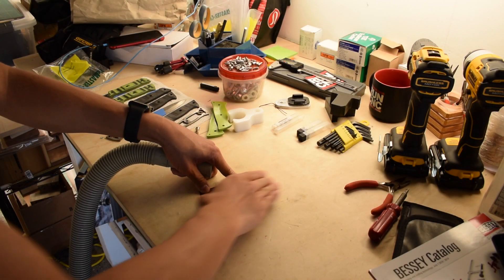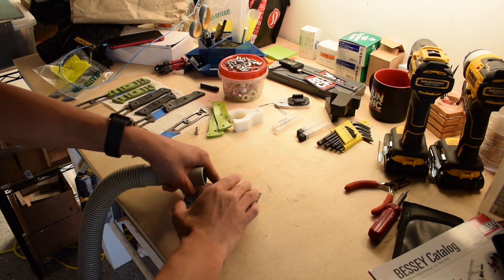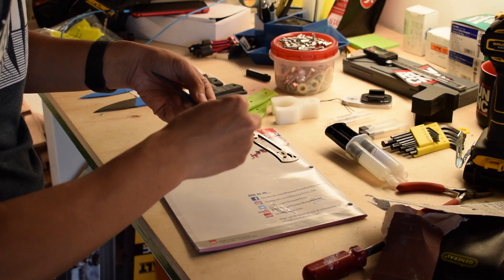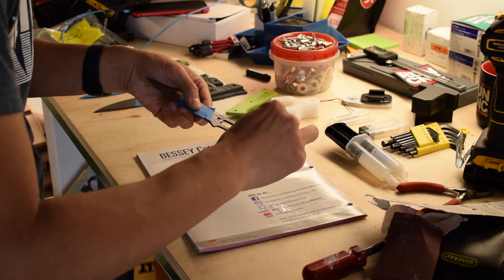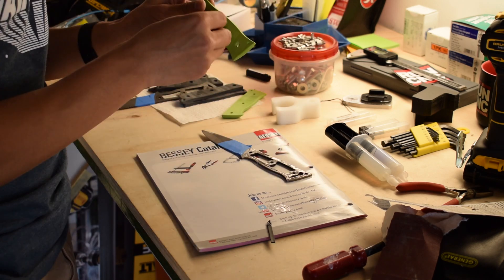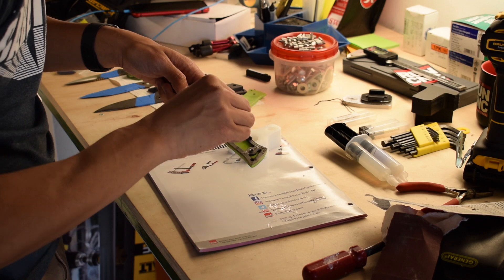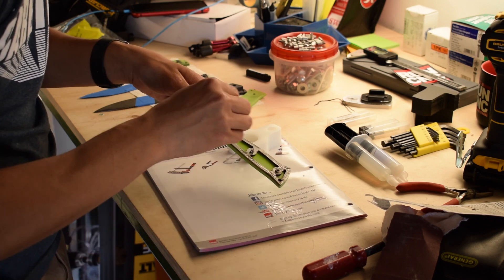To attach my scales to my knives, I first lightly scratched up the interfacing surfaces with some sandpaper. Then I dabbed on some epoxy, smearing it around the perimeter of the handle and around the holes to allow epoxy to form a watertight seal just in case there was a gap between the G10 and the steel. Then I pinned one of the scales in place with corby bolts from one side while I tended to the other side.